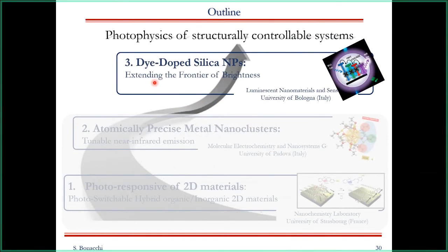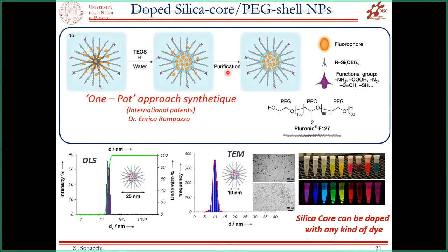And then I move to the last part of my talk, and here we would like to show the possibility to, let's say, not use anymore an atomically precise control on the synthesis of a nanostructure, but again the possibility to play with supramolecular assembly and assembly of molecules to create bright nanoparticles. In particular, I would like to talk with you now about a special case of dye-doped silica nanoparticles. During my PhD and postdoc period at the University of Bologna, in the Luca Prodi group, we optimized a novel one-pot synthetic approach to obtain this kind of doped silica-core PEG-shell nanoparticle.